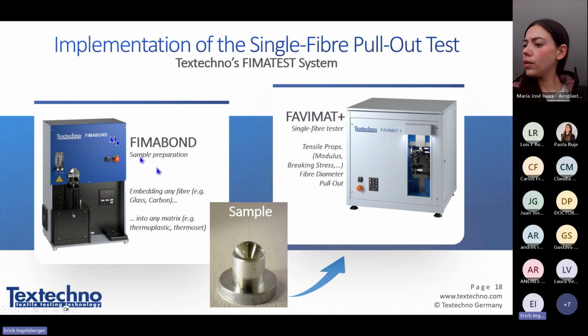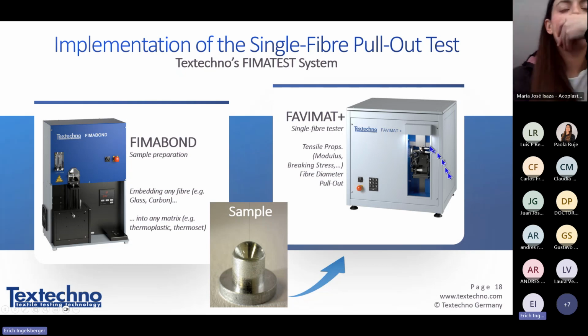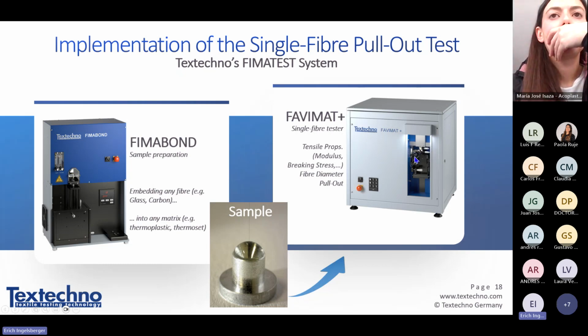However, after preparing this test specimen with the FIMABOND, we then transfer it into our Favimat. As I said, we have a different clamping system here. Now this specimen is turned upside down, so the fiber is hanging down, gripped by a clamp, and taken out of a specimen holder, which you will see in detail right now.